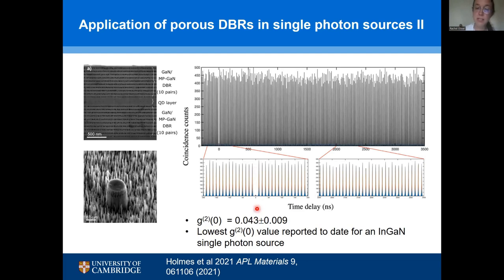And what we want is for the dip to be as low as possible relative to the surrounding peaks. That would be really pure single photon emission. And using these very bright single photon sources that we've achieved using the porous distributed Bragg reflectors, we've been able to tune the excitation conditions to get the purest single photon stream that's ever been reported for indium gallium nitride.